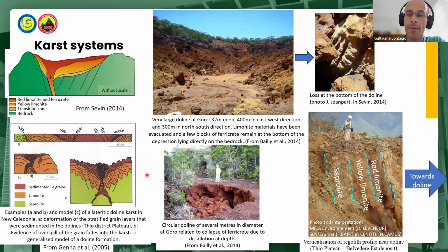So these are illustrations of dolines, which is one of the most common exokarst features in nickel laterite, generally developed at fault intersections. You can see on these pictures a huge doline at Goro in the south of New Caledonia with laterite at the bottom of the doline. Another example of doline here, and this is in Thio deposit, one of the deposits at Thio on the east coast, with verticalization of the regolith profile near a doline. Genna and Sevin modeled doline formation and geometry as shown in these figures on the left. And one noticeable feature is deepening and disruption of the regolith layers.